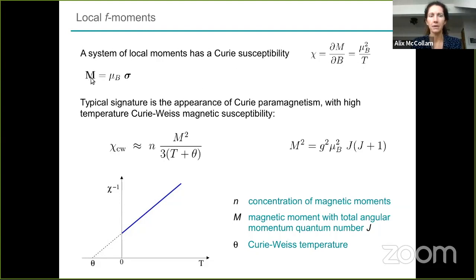M is the magnetization, this is the Pauli matrices. This gives you a Curie-Weiss paramagnetism developing, and I said that this really just appears at high temperature, but when you are at high temperature, you have something that looks a little bit like this, where this is the concentration of the magnetic moments, and this is the Curie-Weiss temperature. So if this is negative, then you have an antiferromagnet, and otherwise it's ferromagnetic. This is the angular momentum quantum number, and this is the G factor. So that's the Curie-Weiss susceptibility at high temperature.